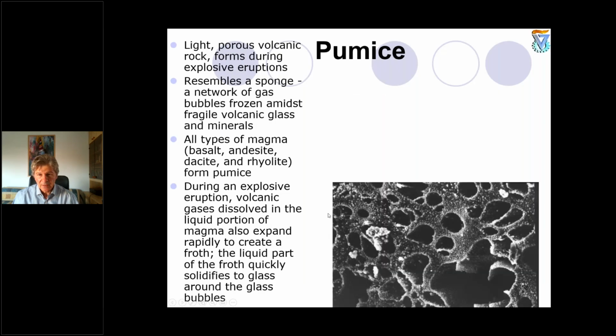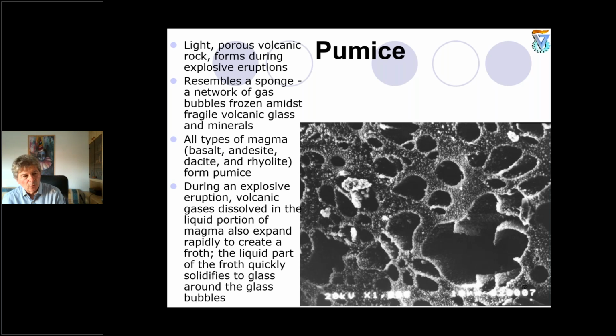What is interesting, this pumice particle is formed from magma erupted from volcanic origin material, and then the hot gases penetrating through this volcanic material leave behind these open pores looking as tubes, very long tubes. So most of the porosity, and this is very important to understand, this is very needed for having efficient internal curing, most of the porosity is open. We prefer open pores over closed pores.